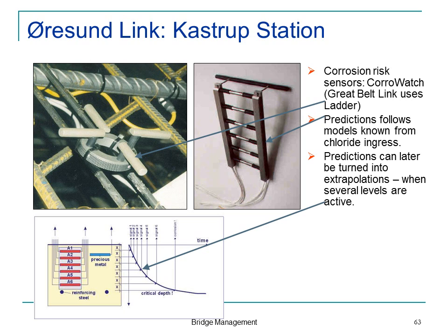This means we can actually measure the potential. Already years ago, that potential was such that we said in normal conditions it would be severe corrosion. But we could also measure the corrosion rates, and they revealed that there was just about no corrosion going on.